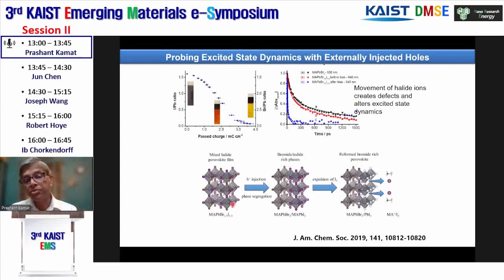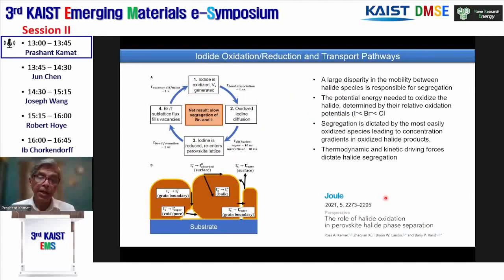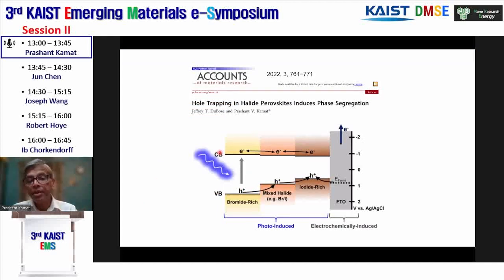So to summarize, the mixed halide forms, you inject holes, you form this phase segregation and eventually this leads to aggregation. Recently, Barry Rand and his group have published a Joule perspective identifying how halide chemistry dictates the performance of the solar cells. And again, this iodide gets oxidized. It is again trapping of the holes, and the oxidized ion diffuses, and then iodine is re-reduced and re-enters the perovskite lattice, and again the cycle continues. To summarize, the hole trapping in halide perovskite induces phase segregation. This is an Accounts of Materials Research article that we recently published, and please take a look at it.